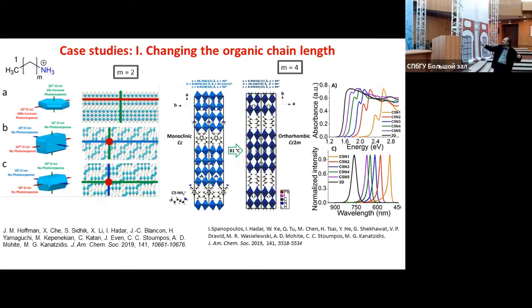You see discrete emissions at specific wavelengths that depend only on the well thickness, but not on the barrier. You can have them 1 angstrom, 2 angstrom, 3 angstrom different, nothing happens. So it's not important, and that's interesting. So somehow the barrier doesn't play a role.